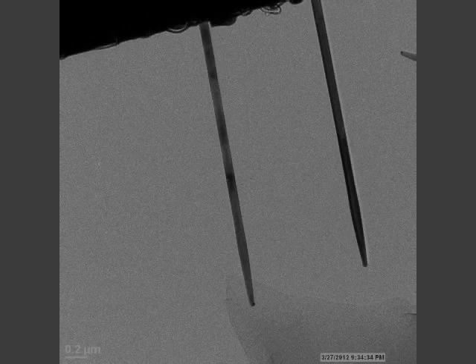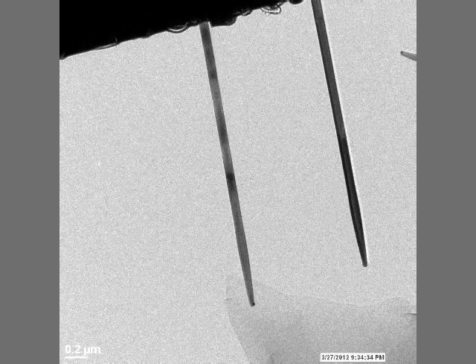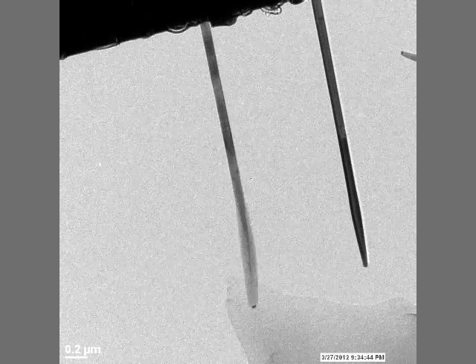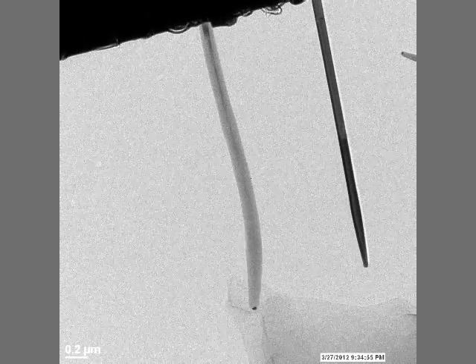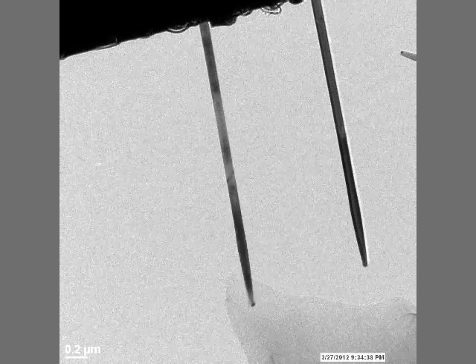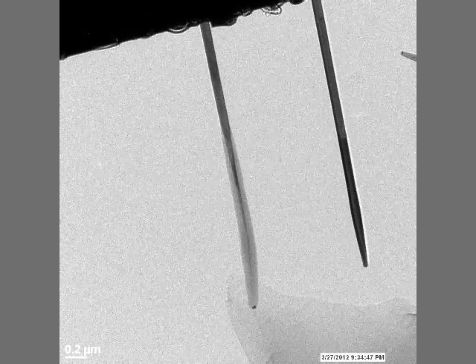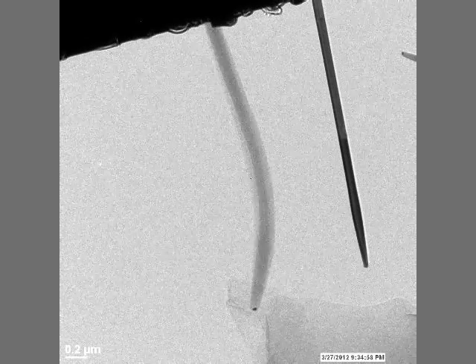In the first video, where we see two nanowires, one of them has a lithium metal that's connected just at the tip of the wire. And as we play the video, we start to see that a lighter contrast starts to appear at the surface of the wire. That means that lithium ions are diffusing from the surface into the nanowire core.